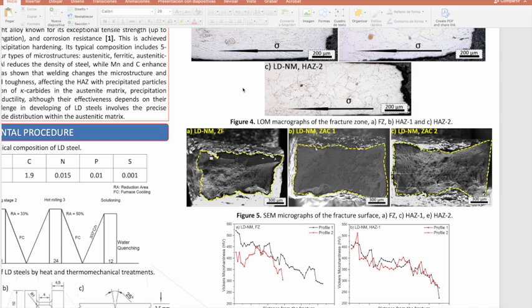Typically, these dimples form due to the presence of precipitated particles, but after a tensile test, these particles create voids that become visible and can be of different sizes according to the particle size. This type of morphology favors ductile behavior and increases the percentage of elongation reached.